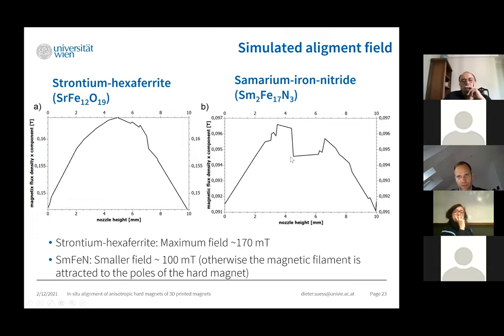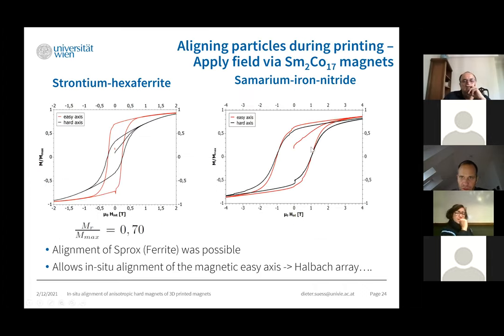We have to put the magnets further away, and we can only allow for 100 millitesla. And this also had a very bad consequence, because for the samarium iron nitride, we could not align the particles successfully.